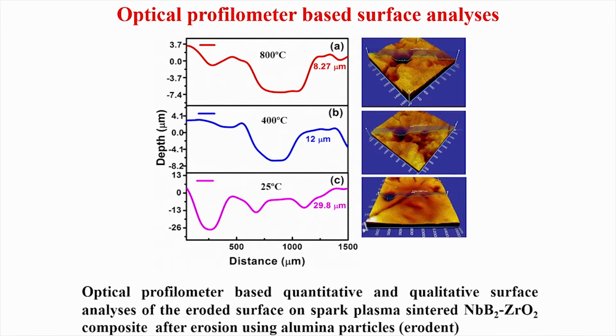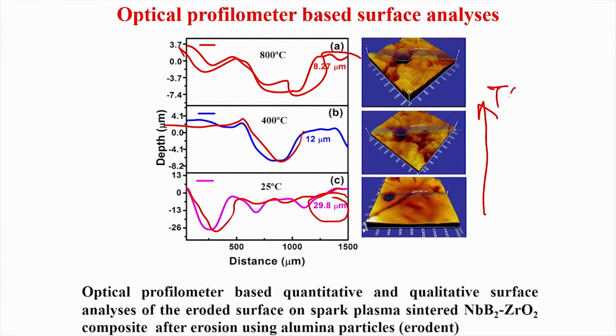Okay. This is the optical profilometer based 2D surface analysis at different temperatures, from 25 degrees Celsius to 400 degrees Celsius to 800 degrees Celsius. What you notice here is that at 25 degrees Celsius it is 29.8 micron, at 400 degrees Celsius it is 12 micron, and at 800 degrees Celsius it is 8.3 micron. So, if you increase the temperature, the erosion wear depth, that micron value, decreases.